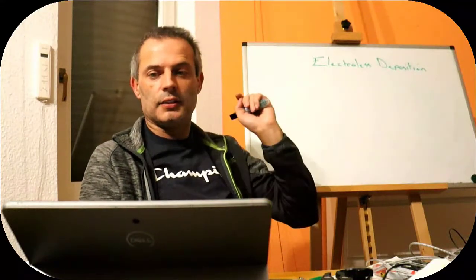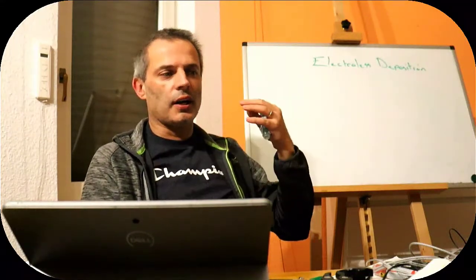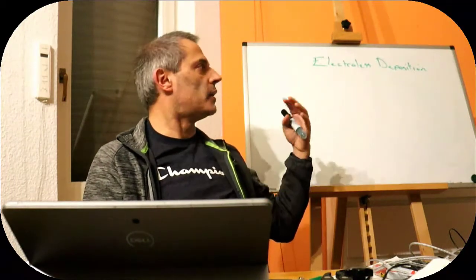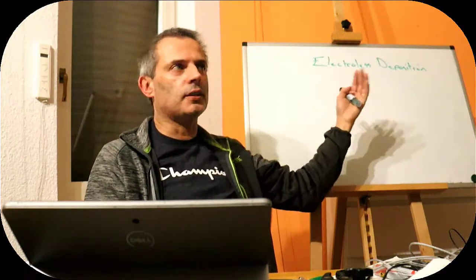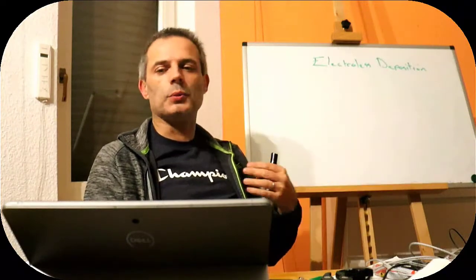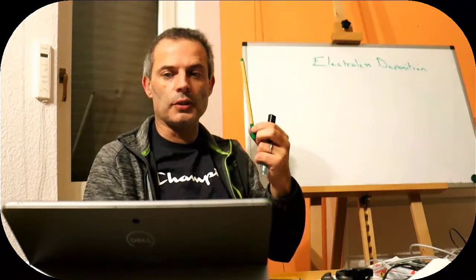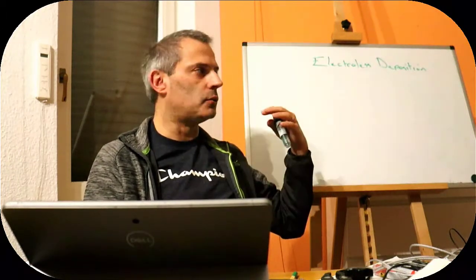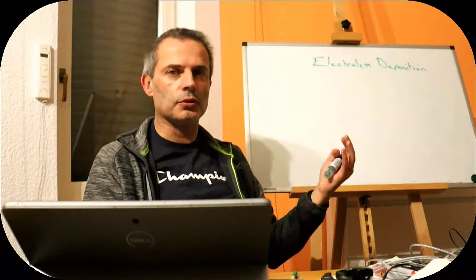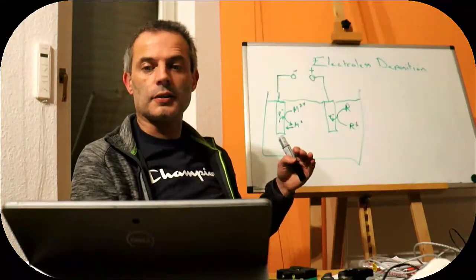The standard technique is electroless deposition, and it works in the same way as electrode deposition, in that we have a metal ion in solution and it's going to be reduced. But because we don't have an electrode, we don't have anything to make electrical contact to a piece of polymer, then we need to do the reduction in solution as well. So here's the standard setup.